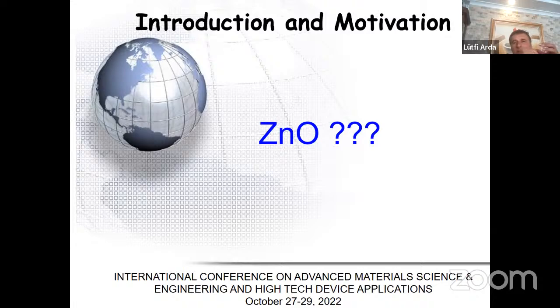In this method, there are many synthesis parameters, including seed deposition, growth temperature, growth time, molarity, etc., which are important in governing the structural properties of the films. The structural property of zinc oxide thin films strongly depends on the crystal quality of this compound and impacts the optoelectronic characteristics in surface engineering applications. Moreover, in the hydrothermal route, it is expected to manipulate the optical properties of zinc oxide nanorods by changing only the synthesis parameters, without adding any impurity to the crystal structure. In this work, we use the hydrothermal route.